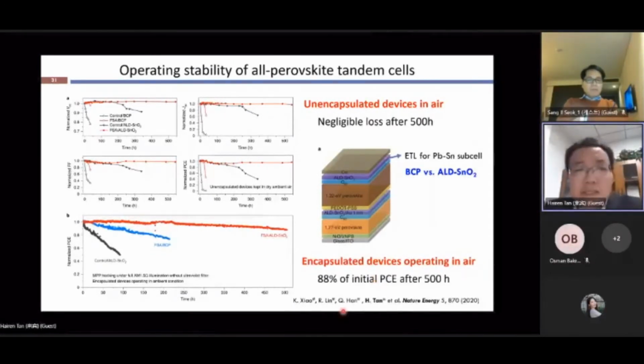Actually, we found that this may not be a major issue if we can encapsulate the devices well. We also found that the charge transport material is very critical for device stability. For example, if we replace the organic BCP with metal oxide materials, even for unencapsulated devices stored in air for 500 hours, we can see that the performance degradation is negligible.